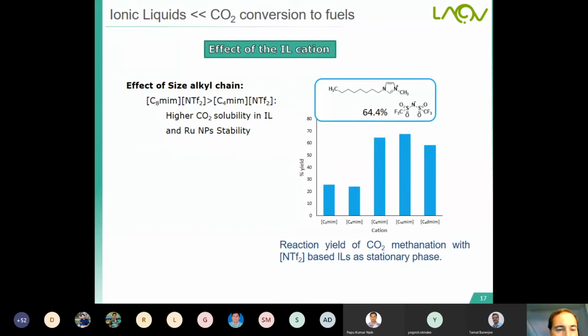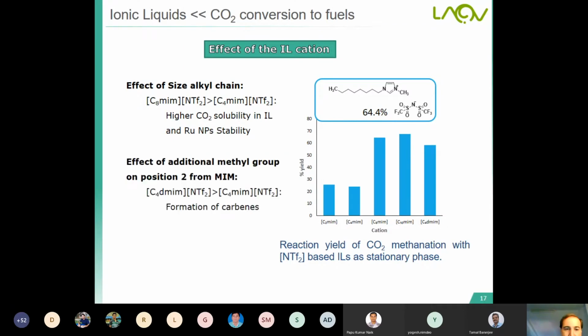C8 is better than C4 because we have a higher CO2 solubility in the ionic liquid and a higher ruthenium nanoparticle stability. But also the effect of an additional methyl group on position 2 here in the imidazolium cation, between the two nitrogens: the C4DMIM, compared with C4MIM, is better because we can avoid the formation of carbenes.